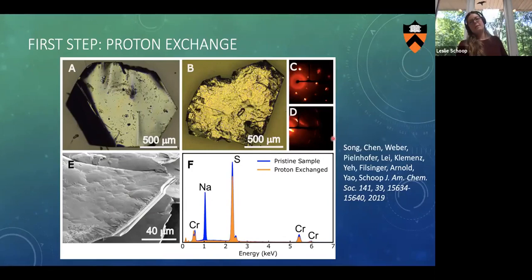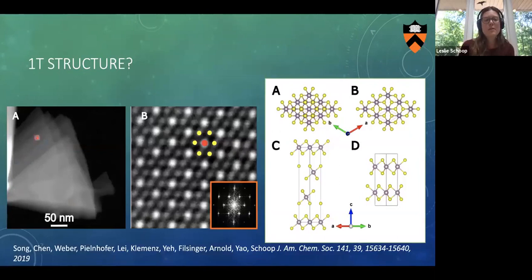So what we did instead to understand this material was we took it to the transmission electron microscope, where you can directly look at it. So here you see the sample in a lower magnification, lower resolution image. And you see it's actually a very nicely layered material. And then you can zoom in and you can look at the individual atoms. And so here you see bright spots and faint spots. And because heavier elements appear brighter in the TEM, you know that this one is chromium and these faint spots are sulfur.